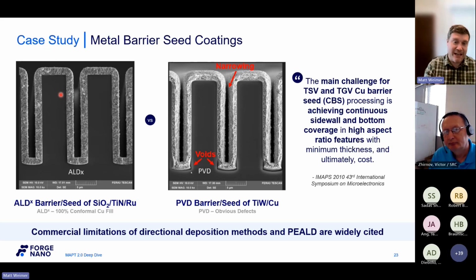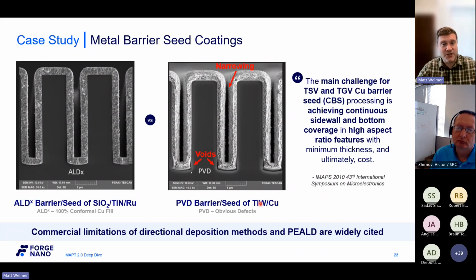Now, typically you need an adhesion to your adhesion layer. So a typical solution is PVD, where your seed for copper is also copper, but you also have an adhesion layer for that copper with a Ti tungsten, just one example. Fortunately, that Ti tungsten is also a copper diffusion barrier, so it gets to play two roles there. In our silicon example, we also need a dielectric, so there's a thick silicon dioxide. However, we can think about using ALD for the same solution.